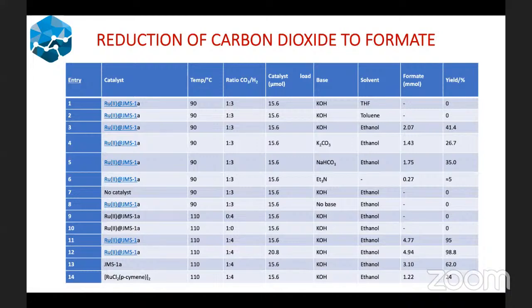We noted that maybe the triethylamine does not have access to the metal hydride, which is located inside the pores of the MOF, because it's kind of bulky. So it's limited from entering into those sites to abstract a proton.